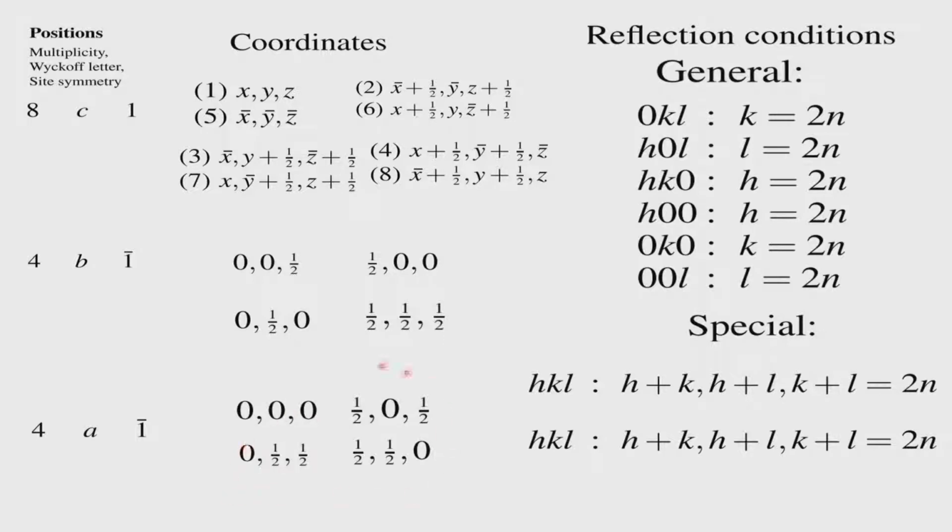Since this is not a face centered lattice, you will get face centered absences in the general reflections, and so it is not an F centered lattice, it is still a PBCA with a special position associated with the Wyckoff A, and that is how we have to interpret the symmetry indications shown in the International Tables for Crystallography. Now you see the importance of analyzing the equivalent points, their presences and absences, and then identifying the space group to the extent possible.